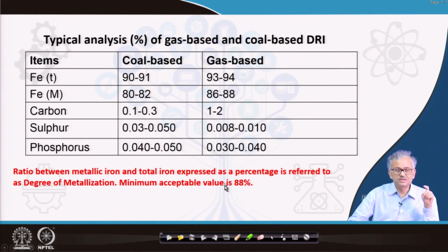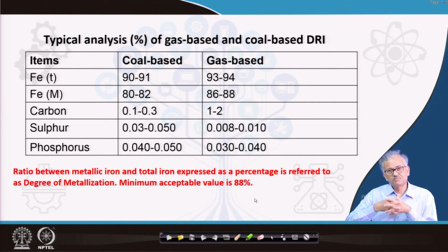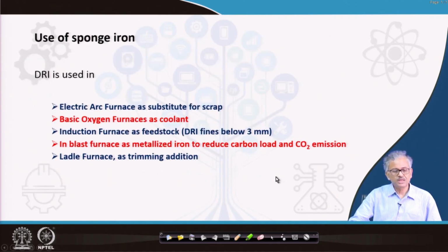The ratio between the metallic iron and the total iron is called the metallization, and minimum acceptable is 88%. Metallization minimum should be 88%, otherwise a large amount of iron will be combined with the oxygen in the form of wustite, and then that increases both the thermal and reduction load of the electric arc furnace, and sometimes it may not be economically viable.